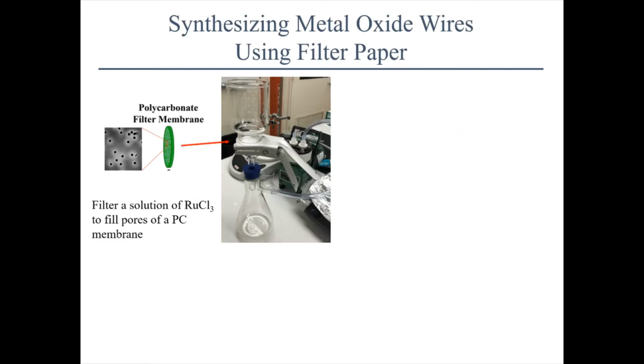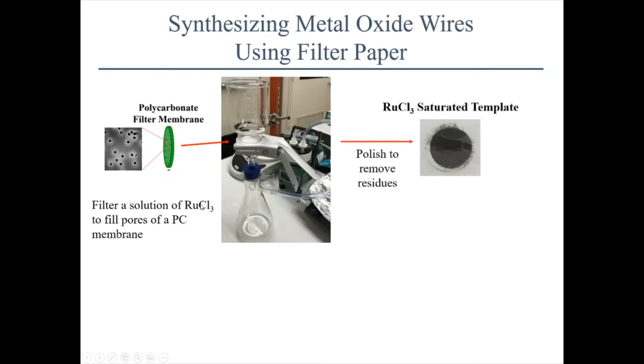So to introduce you to how we synthesize our ruthenium oxide substrates, what we did was we took a polycarbonate filter membrane, which is something you can buy commercially. It's basically a filter membrane with tubular pores. And we used vacuum filtration to saturate the pores with ruthenium chloride. Basically, we took a solution of ruthenium chloride and we used a vacuum to pull it through and get the ruthenium chloride into the pore itself. Then we took that template out, dried it, and we polished the outside to remove any residues. This allowed us to get a very high morphological purity of just ruthenium oxide nanowires.